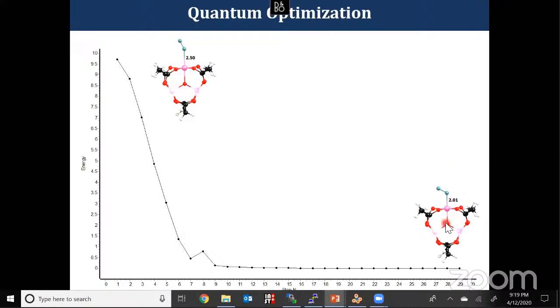So what happens from this energy to this energy? Initially the crude structure has higher energy. When we start the optimization, all the bond lengths, bond angles and torsions will relax themselves. It's highly dependent on the method as well as the functional we use for the optimization calculation. If you are using a lower level, the calculation will finish within a minute or more. It won't take more than 10 minutes.